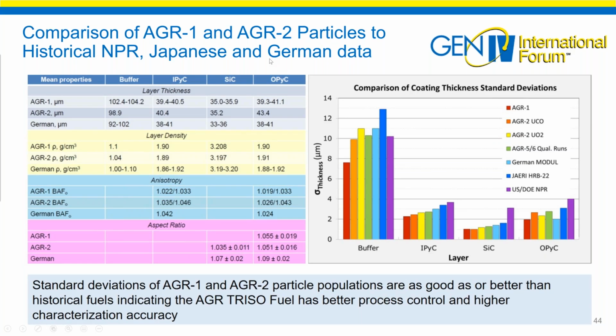So the fuel vendor and fabricator who comes up with a design that has a larger kernel within these layers could do this. But if you start changing these, the way the IPyC and OPyC layer will relax, and the things change as you irradiate. And we have this detail. We know what's happening. And if you were to look in the IAEA report, you will see that the particle doesn't grow, but the strength of these layers changes with the fluence. Again, we are well within statistical sampling. We've got a tighter control of our process, for instance, than the German and the Japanese data or our earlier US data. So you have to have good process control.